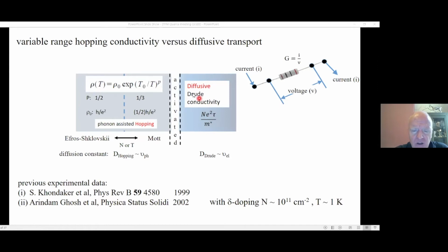As we cool down the sample, go to lower temperatures or to lower carrier densities, what we find is that some of these quantities become thermally activated, so we pass through a thermally activated region. It could be an intrinsic semiconductor, where we've got carrier activation, thermal activation across a band gap. It could be carrier freeze-out through doping. We pass through an activated region into the metal-insulator transition. And in the metal-insulator transition region, we describe the system with a mechanism called hopping. So the charge hops between vacant states in the lattice. And interestingly enough, we describe that by an exponential.